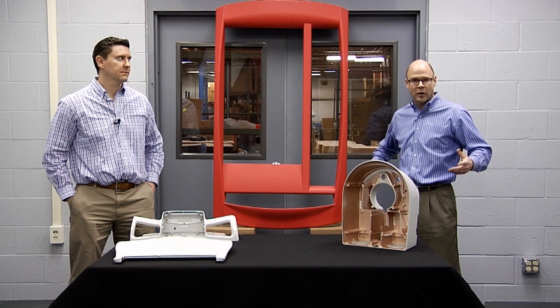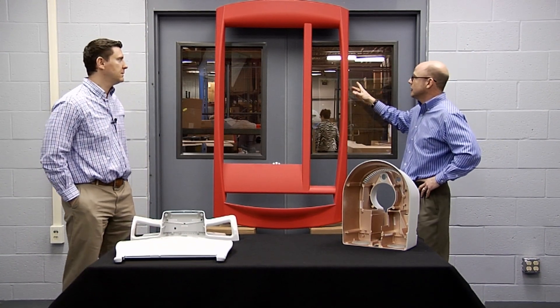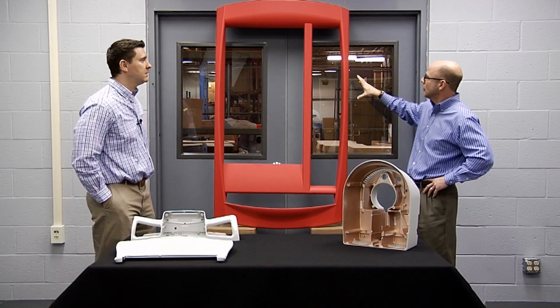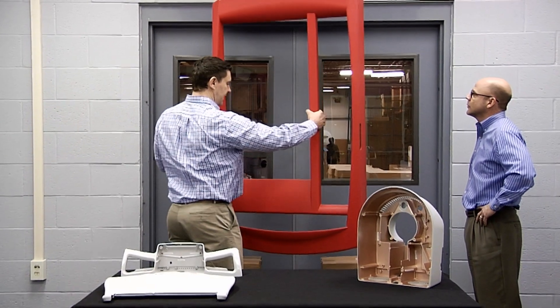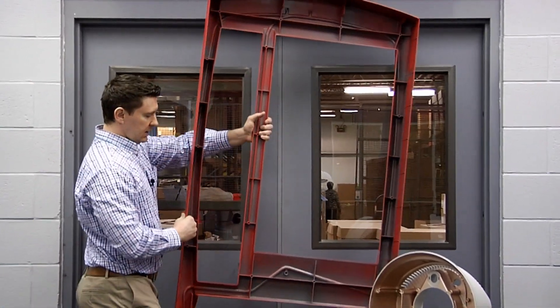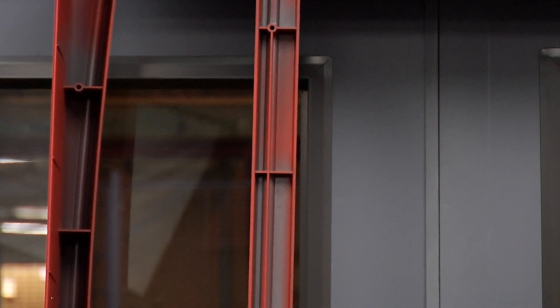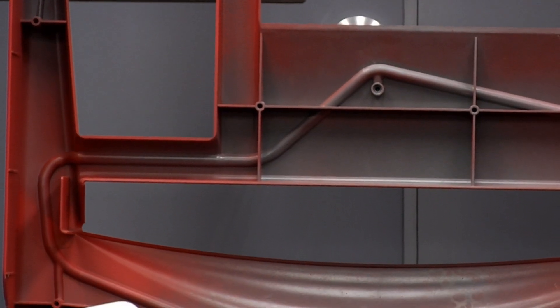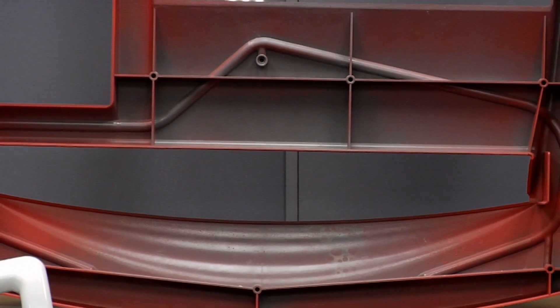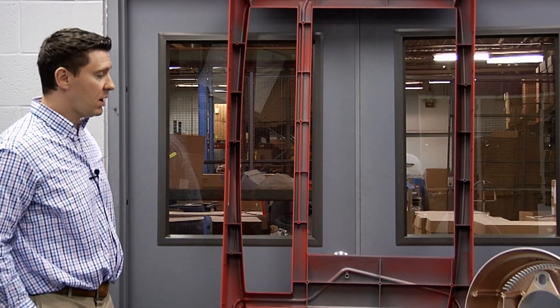The first category of parts we're talking about are large parts. Behind us here we have a large gas-assist injection molded part. This part has two valve gates and is molded in a 1500-ton press. With straight injection molding, you take the projected area — length and width in the direction of pull — and multiply by three and a half to four and a half tons per square inch, which would lead to maybe a 3000-ton press. With gas-assist, the typical ratio is approximately one-to-one based on material viscosity, so we're able to mold in a smaller press and save cost.